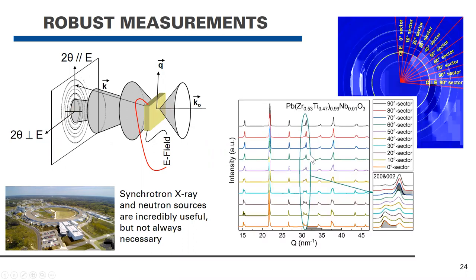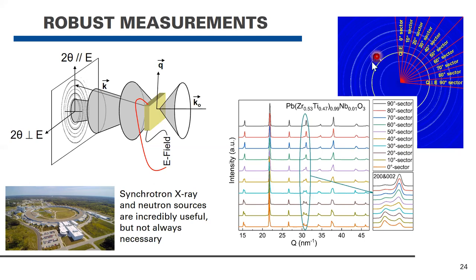So if you look at the raw data, you can see that, for example, again, sticking to the tetragonal case, you can see a change in intensity of the 002 and 200 peak as a function of angle. And here we're representing the angle as a sector. So we're discretizing what was formerly a continuous distribution of intensity.